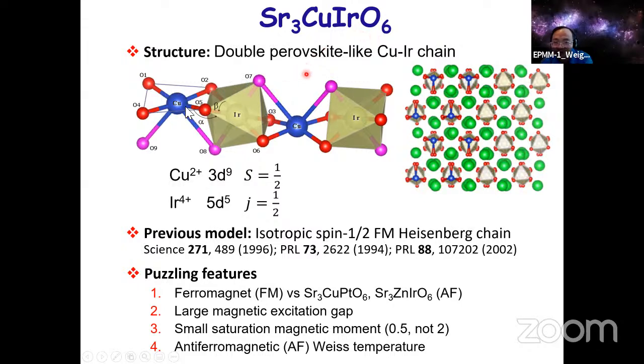And then for this material, for example, this is a copper. The blue circle is copper, and then this is iridium. They form a chain structure. So for the copper, you have a real spin, and for iridium, you have a pseudo spin. So this material is exotic in several ways. One is that it's ferromagnetic, versus the other isostructural 3D and 5D materials, which are antiferromagnetic. Also, this material has a large magnetic excitation gap, in disagreement with the isotropic, gapless spin half ferromagnetic Heisenberg model studied before. And also, it's ferromagnetic, but its saturation magnetic moment is very small. So it's 0.5, not 2. And also, it's ferromagnetic, but it displays an antiferromagnetic Weiss temperature.